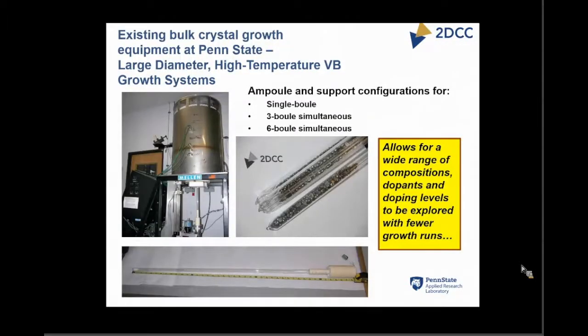So, this photo just shows a little better example of that. This furnace loads from the bottom, translates up into the hot zone, and then comes down through for the growth. And you see here there are 3 ampules that were produced in Tom Maluch's lab, ready for compounding, bismuth telluride with varying composition. And so we can do either single, 3, or 6 in the way that this furnace is configured. Lets you do a wider range of exploration in a single run to quickly generate samples.